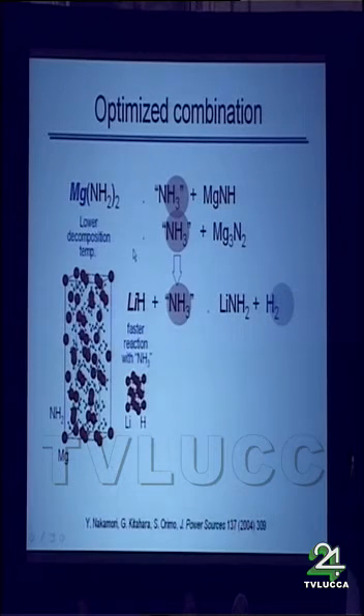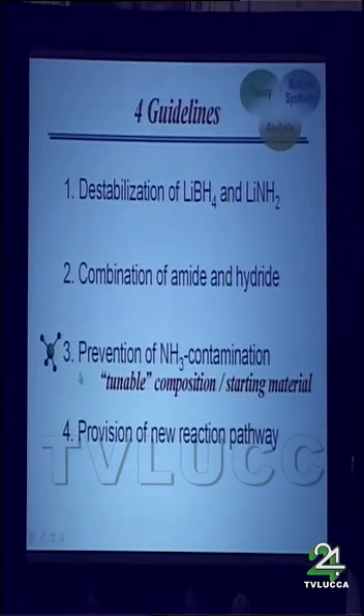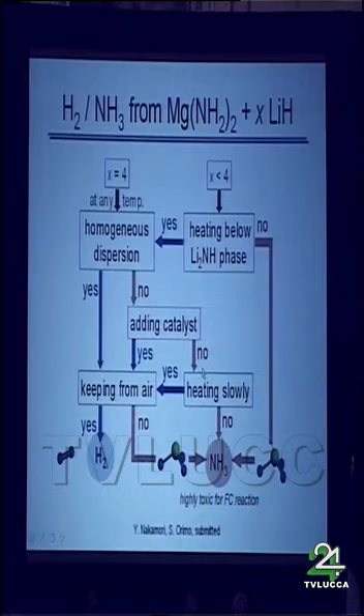So now, the optimized combination is magnesium amide with lower decomposition temperature and lithium hydride having faster reaction kinetics with ammonia. Now, the next question appears: how is the composition ratio? This matter is closely related to the next topic, how to prevent or suppress the ammonia contamination. Here is just a simple yes-or-no chart for hydrogen and ammonia emissions from these combinations. If this X, the ratio of lithium hydride, is equal to 4 or more than 4, the ammonia-like phase from the amide, in this case magnesium amide, can react with lithium hydride. So in this case, it easily comes to here, I mean forming only hydrogen.